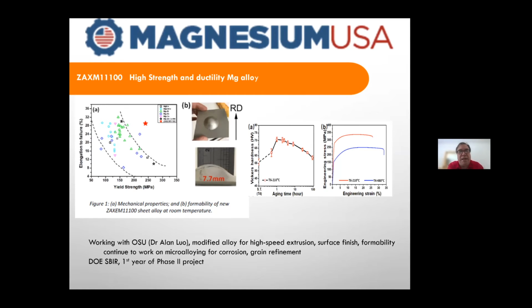One of our newer alloys that we've been working with Department of Energy and Lyft and Ohio State University is a ZACM. It's a low alloy zinc, aluminum, calcium, manganese material that is formable at room temperature. It's designed also to be formable. We've modified this and other alloys to get much higher process speeds during extrusion and eventually in slab rolling. And this is a material that basically in terms of strain to failure, elongation to failure, and strength really forms a new paradigm. It is substantially stronger, lower cost, and more ductile than any existing magnesium alloys.